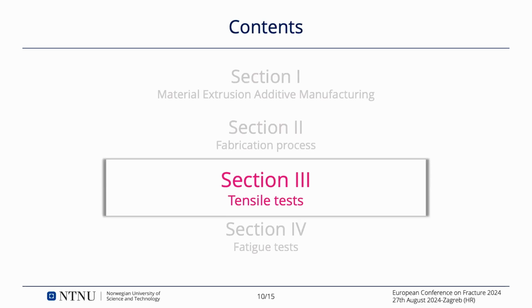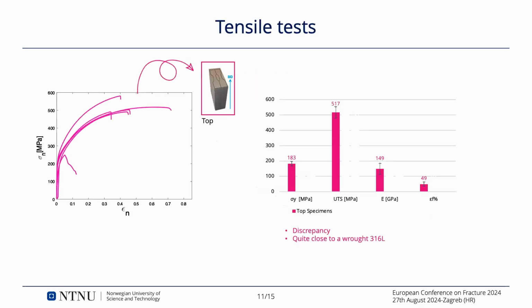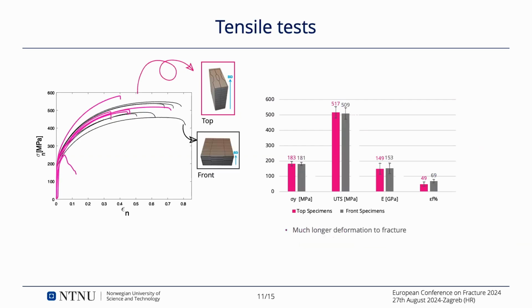So first things first, we performed tensile tests. So we have here the top specimens. And I think it's quite clear. You can see there is a lot of discrepancy, both in terms of strength and in terms of elongation to fracture. And this suggests that the procedure is not really repeatable. Then we have the front specimens, and the front specimens are generally characterized by longer elongation to fracture. They are able to allocate more plastic deformation.